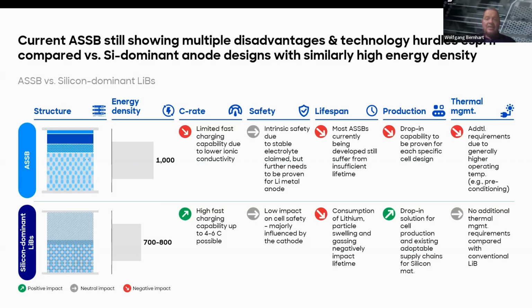From a safety side, there's an intrinsic safety to the stable electrolyte claimed, but that has to be proven for lithium metal anodes on the anode side that really provide the additional energy density. For silicon dominant designs, there's not a big difference. It's to cell safety that's majorly influenced by the cathode. Lifespan cycle life is an issue. We don't have the cycle lives that we can achieve with specific designs with LFP batteries, for example, that are designed for stationary usage. So that's an issue that has to be tackled.